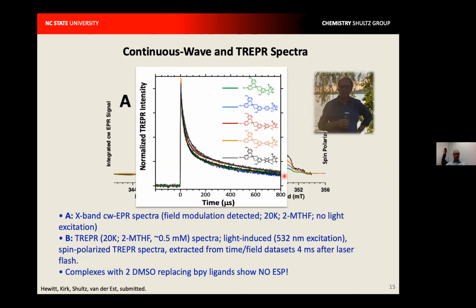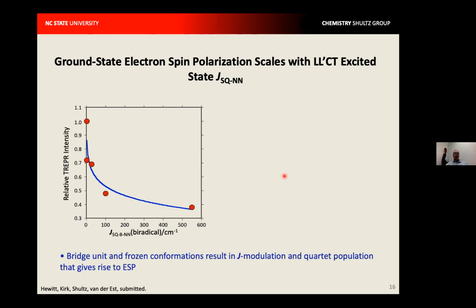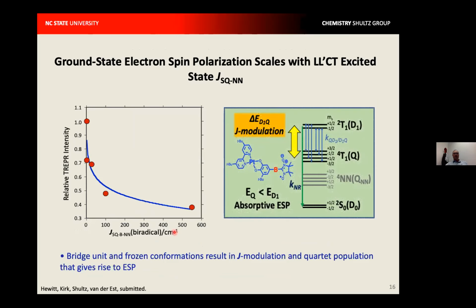So there's a very short preparation time for the spin polarization that lasts for, we think, about 1,000 times longer in the spin polarized ground state. So this is, we think, a nice demonstration of the effect of electron spin polarization that is observed in recovered ground states by photoinduced electron transfer due to exchange modulation caused by both the bridge and frozen solvent solutions.